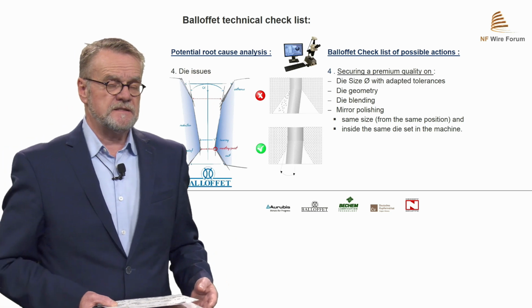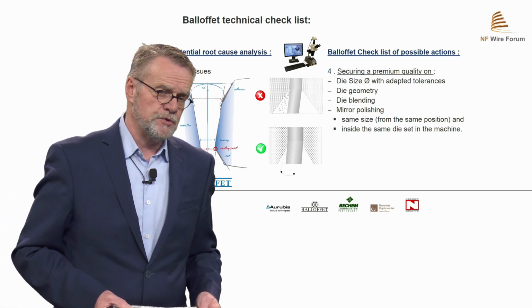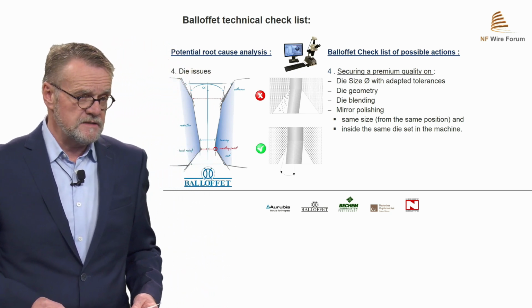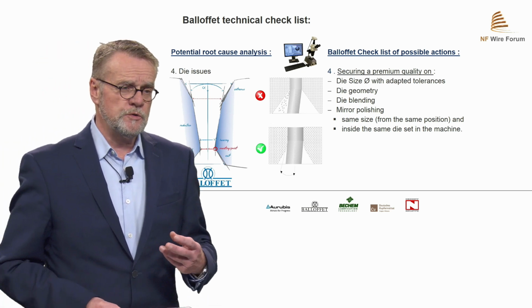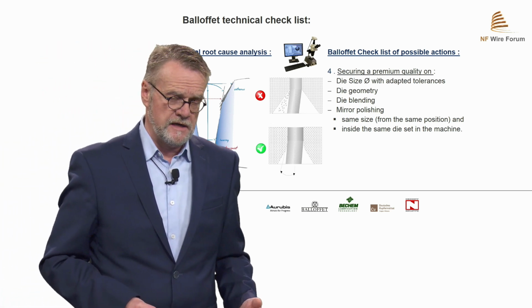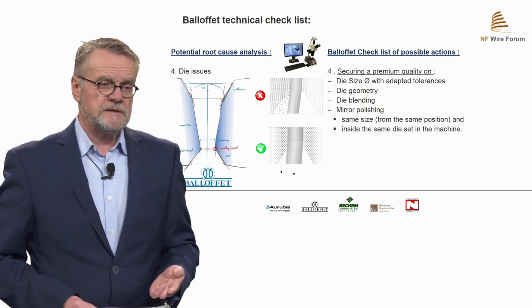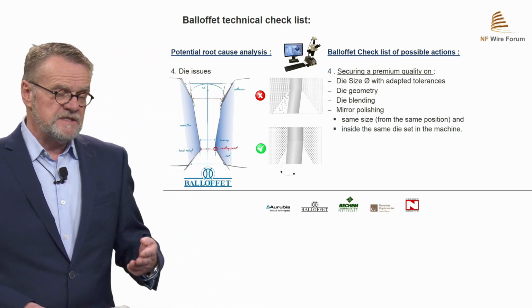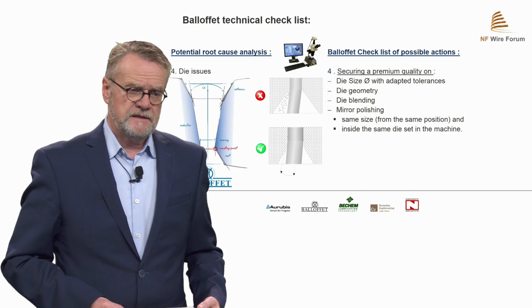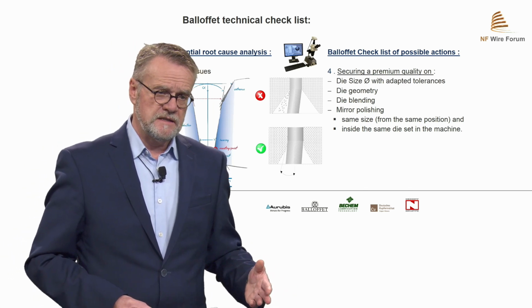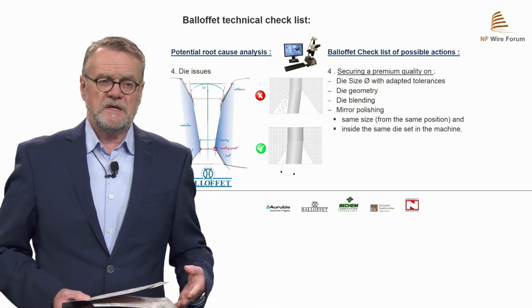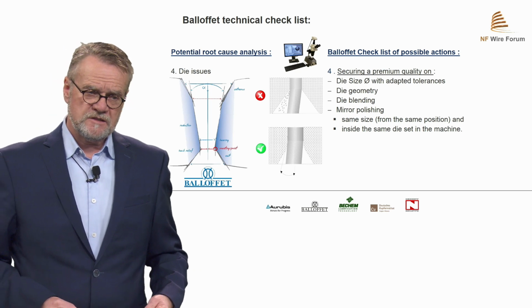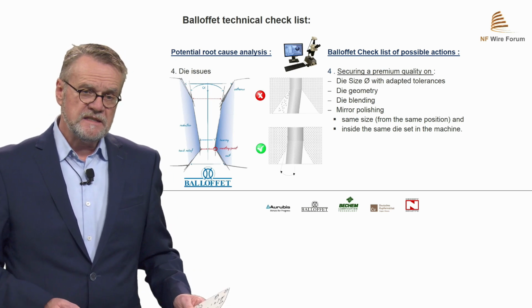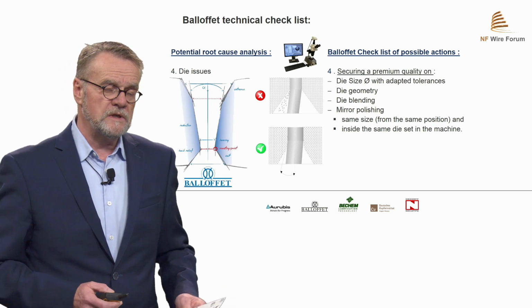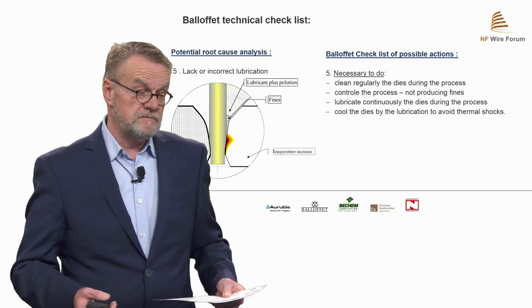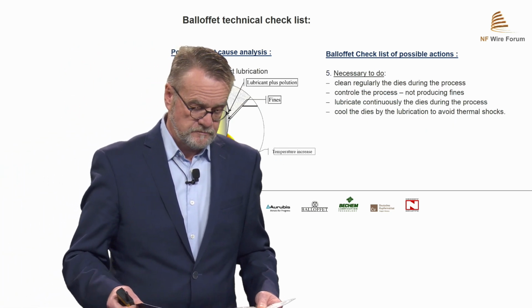And also the exit is very important, because if we produce some fines in the wire process, then we produce the fines on the exit of the die. So it has to be nicely rounded. And what is very important on a die set is that all the same sizes on the same position on the machine have to be respected. And this means not for one set, but for all sets, and in total probably 500.